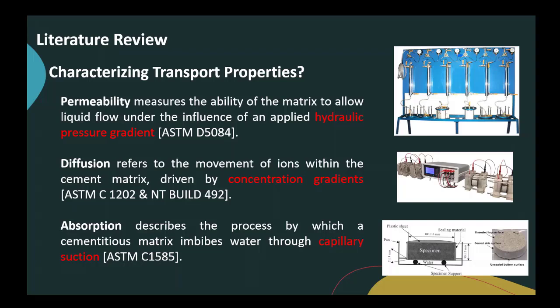But the first two, if you look at the apparatus or the equipment, can cause error for many reasons. For the last one, you just coat all the faces except the bottom one, and the dry sample touches water and absorbs liquid. We measure this absorption as a function of time. That's called absorption, and it's well explained in ASTM C1585. It's purely based on capillary suction. There are some theories that say there are different mechanisms, but scientists believe that this is purely capillarity.